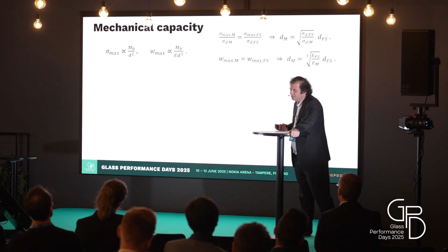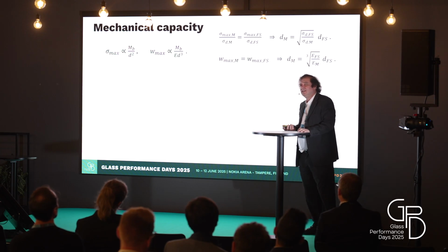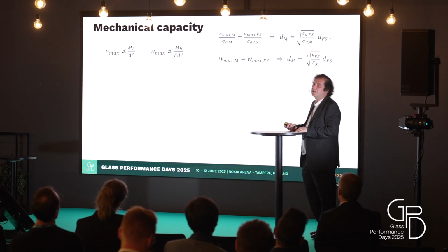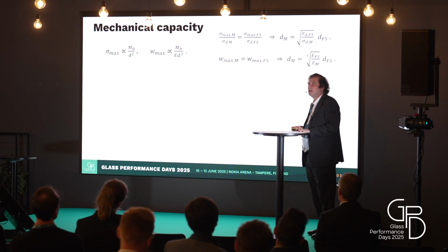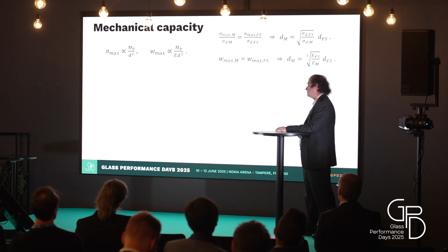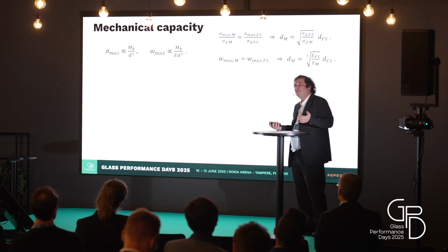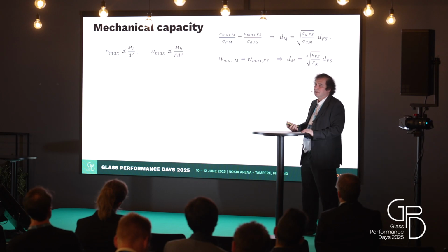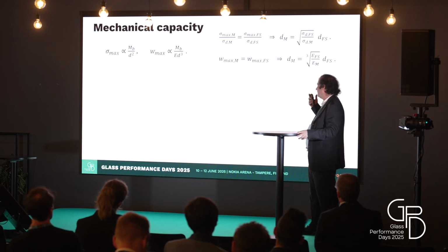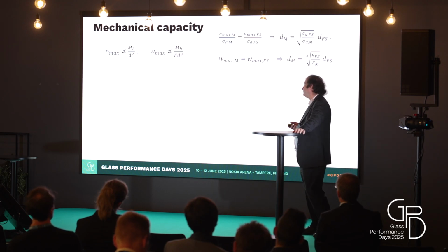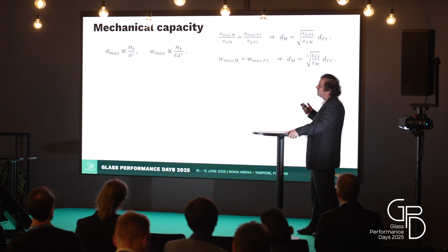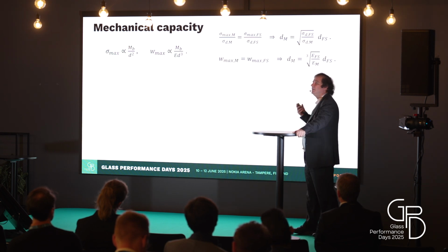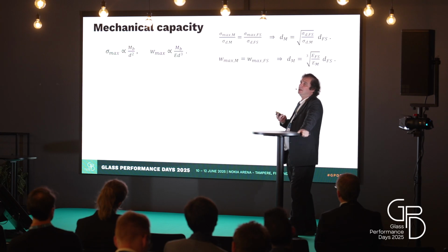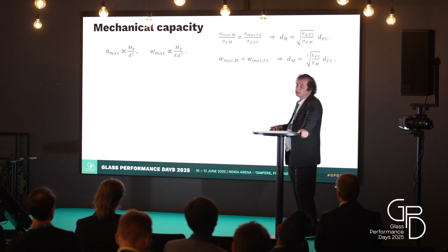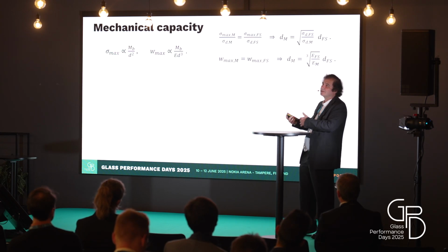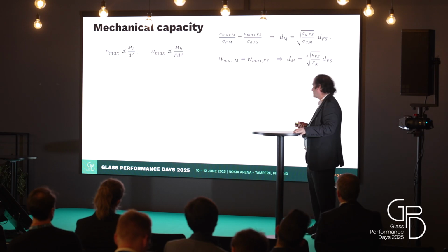Also, if you take into account the mechanical capacity, well, the problem of acrylic glass compared with fused silica is the low elastic modulus. And of course, you know that the stiffness goes with the cube of the thickness of the element. So if you want to compare the mechanical capacity in terms of stiffness and strength of fused silica and acrylic glass, you have to consider different thicknesses.